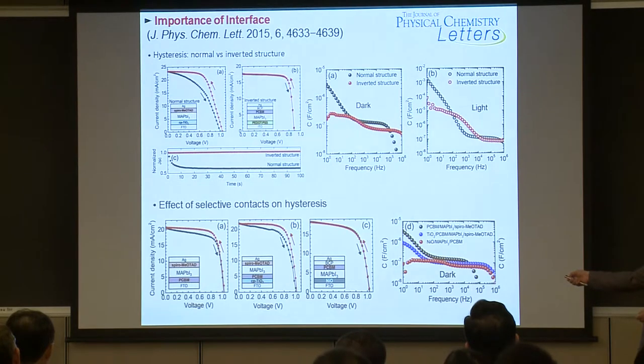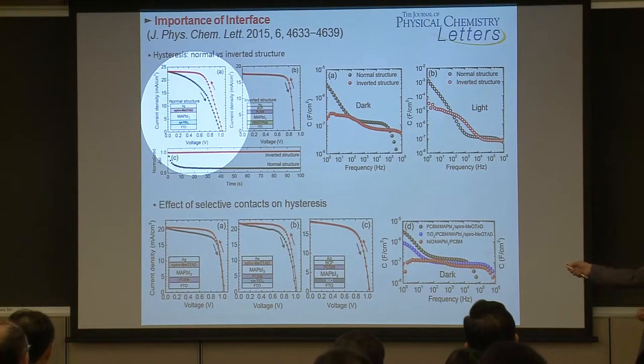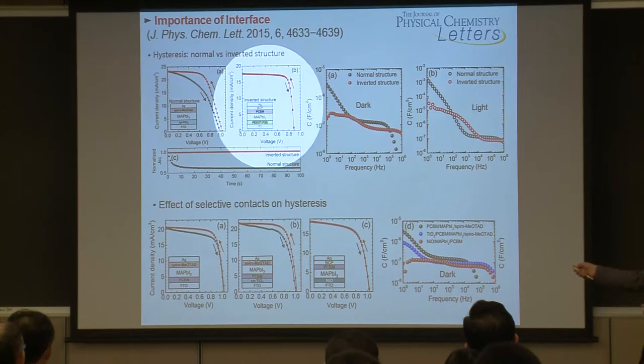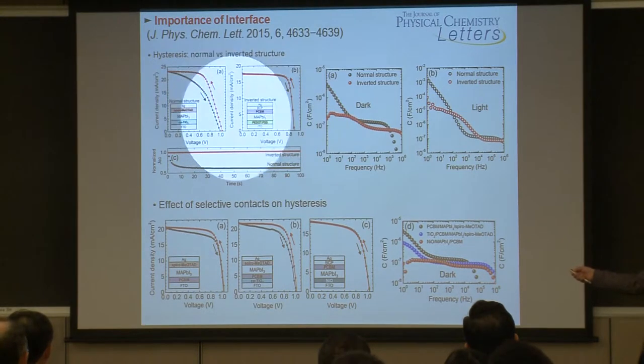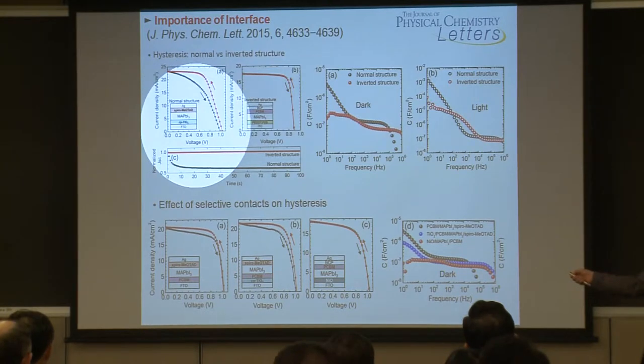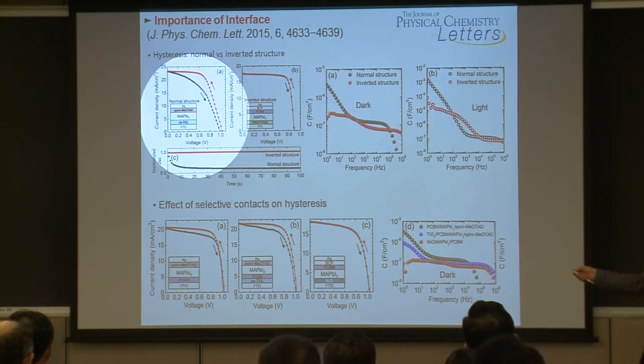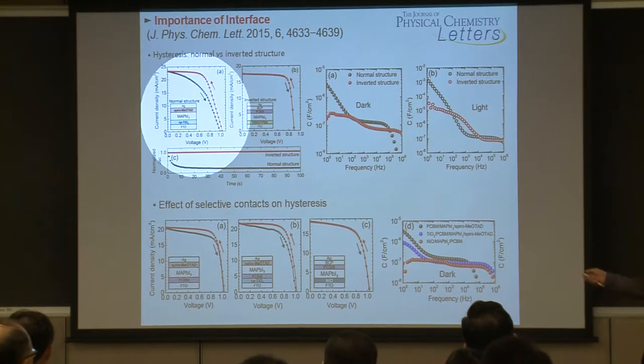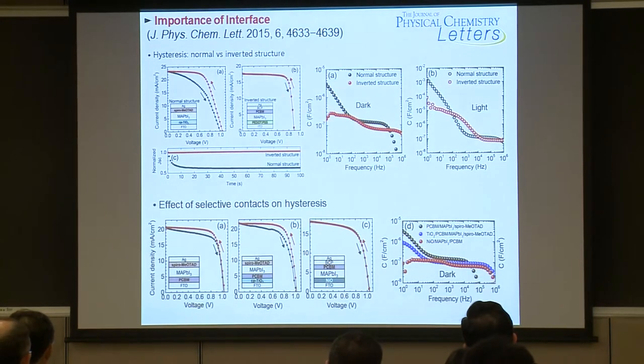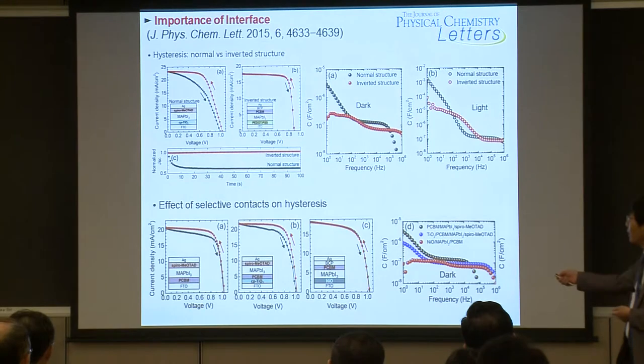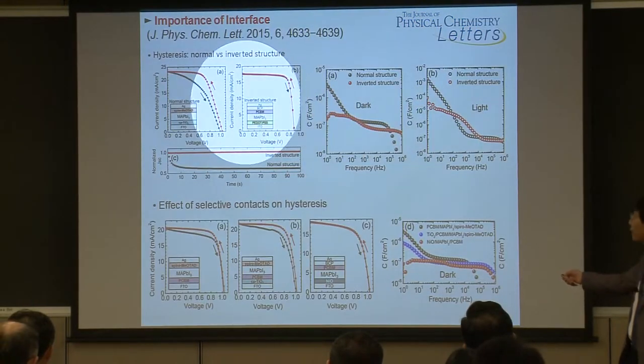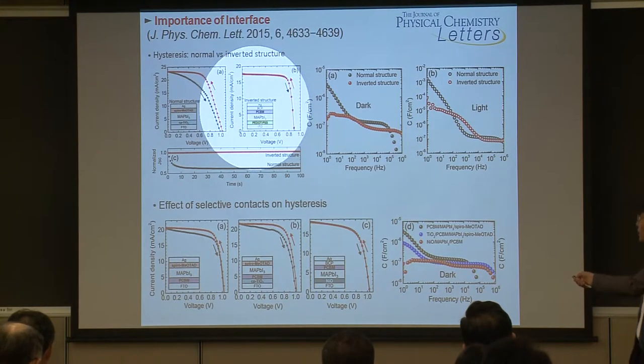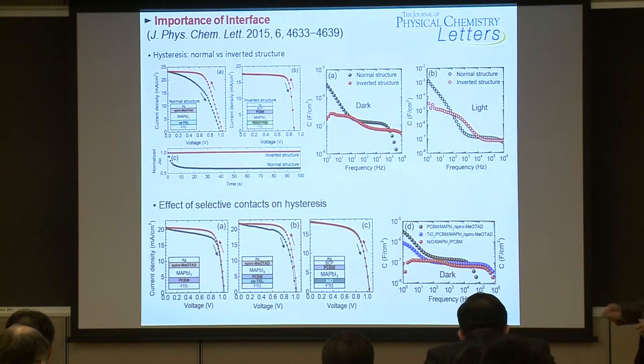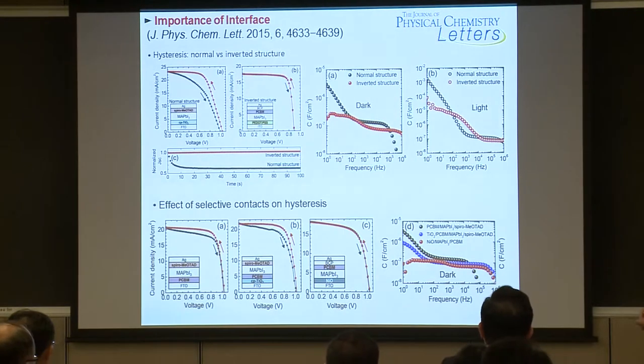Anyway, for instance, the perovskite solar cell, you can make the normal structure or inverted structure. Normal structure means the FTO conducting glass with the electron transporting layer such as titanium oxide, and then the top layer is a spiro HTL, hole transporting layer. The inverted structure is a different configuration. The hole transporting material is deposited on FTO conducting glass, and then the top electrode is the ETL layer.